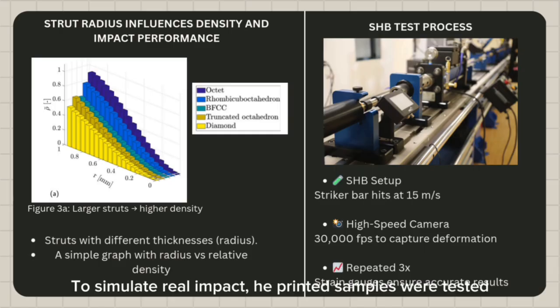To simulate real impact, the printed samples were tested using a split Hopkinson bar or SHB setup. The striker bar hit the samples at a speed of 15 meters per second, compressing them up to 80%. The impact response was recorded with strain gauges and a high-speed camera at 30,000 frames per second. Each test was repeated 3 times to ensure consistent results.